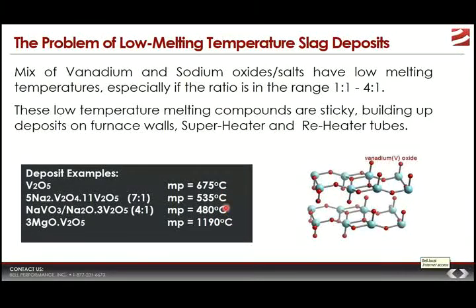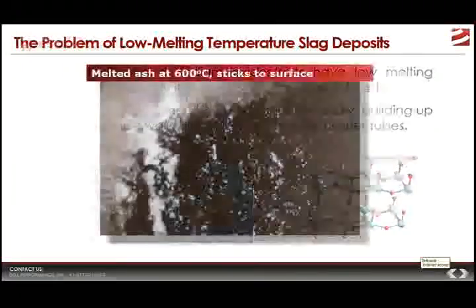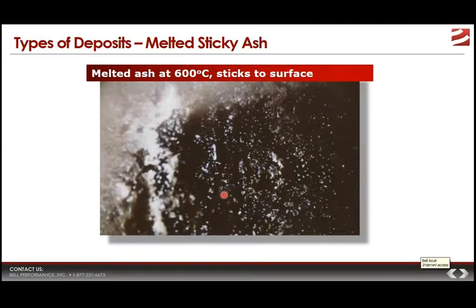So when an HFO user has deposits like these with low melting points, these low melting point deposits or compounds have problematic physical properties. They're sticky. They build up on furnace walls, and they provide a sticky substrate for additional ash and additional deposit forming components to stick and build up on furnace walls and superheater and reheater tubes, all of those kinds of things. Typically the danger zone for this happening is when you have a vanadium to sodium ratio between 1-to-1 and 4-to-1 by weight.